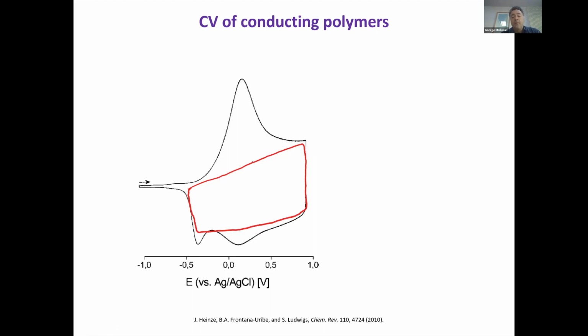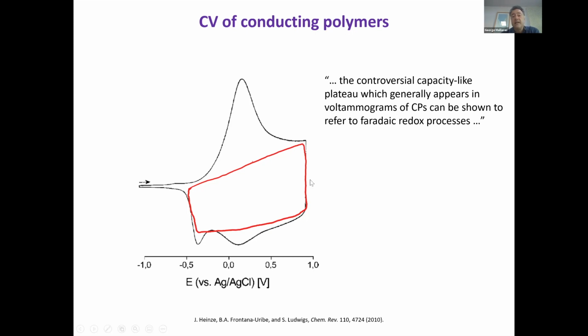So here opinions are divided. I think the majority of people will tell you that you have a mixed response, a pseudo-capacitance. There are different terms that are used to imply that you have a bit of both, a character that is both Faradaic and capacitive. But there's not necessarily consensus. Here's one example from a review paper, where it states that the controversial capacity-like plateau, this red area here, which generally appears in voltammograms of conducting polymers, can be shown to refer to a Faradaic process. So according to this school of thought, everything is Faradaic, there's nothing capacitive.